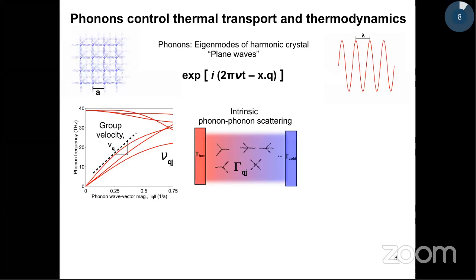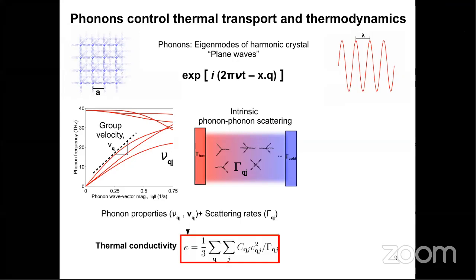So these phonons in a real material also undergo interactions among themselves because no real material is perfectly harmonic, and they always have some inherent perturbative anharmonicities which drive these phonon-phonon scattering processes. So these phonon-phonon scattering processes can occur among 3 phonons at a time or 4 phonons at a time and so on. And a net total of all of these scattering processes can be summed up to give a single quantity gamma, which is the total scattering rate. So knowing these properties like phonon frequencies, group velocities, and scattering rates, you can put them together into a kinetic theory expression to calculate the thermal conductivity of any material. So the expression here shows the thermal conductivity of a material is represented as a sum over all phonon modes in the crystal, that is the sum over the wave vector and sum over the polarization J, of heat capacity times velocity squared divided by the scattering rates.